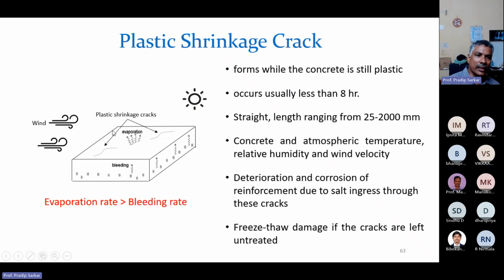You know, plastic shrinkage occurs when the evaporation rate is larger than the bleeding rate. So we don't have sufficient water on the top surface. Because of evaporation, whatever the bleeding water is, the bled water will be evaporated, and there will be plastic shrinkage cracks. And this plastic shrinkage usually forms in less than 8 hours, while the concrete is still plastic.